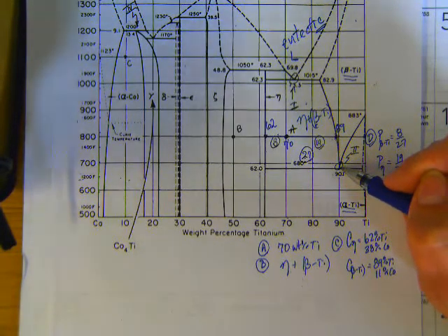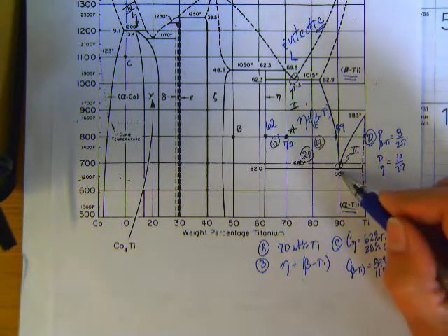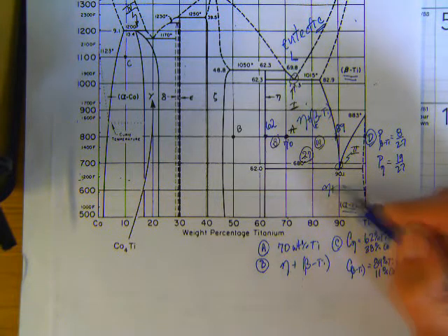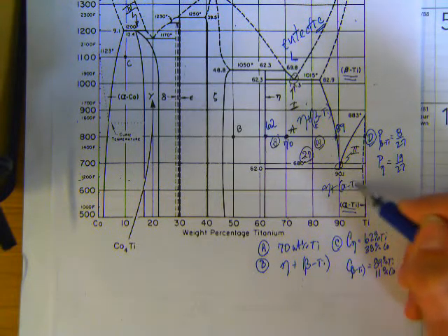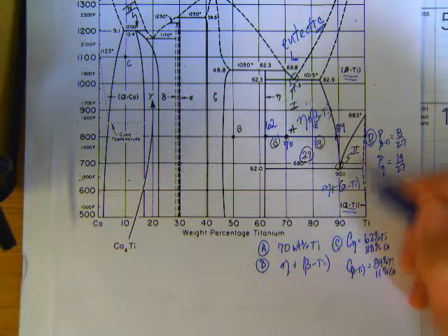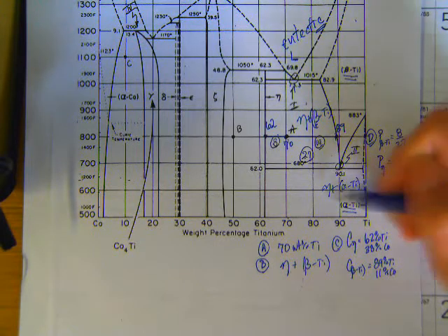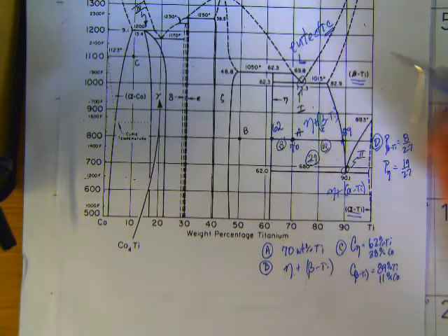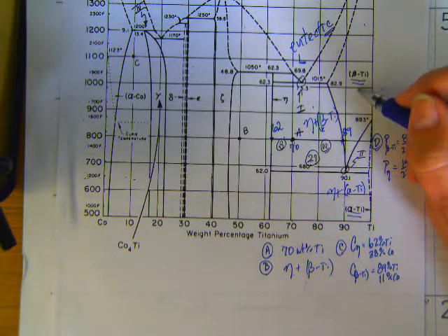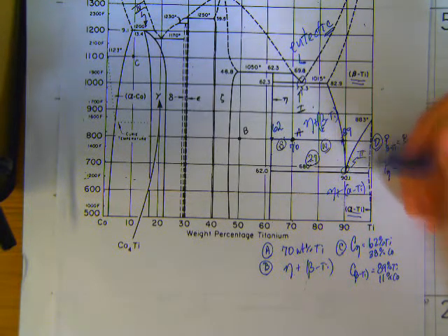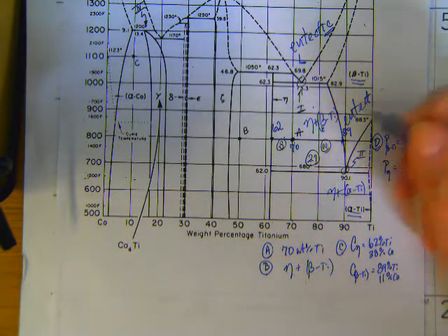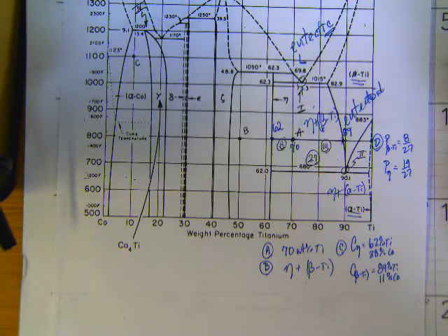Now we have an invariant down here at 90.1. Again, single phase, beta-titanium above. Down below, we now have eta plus alpha-titanium. So there's a crystal structure change. There's a big solubility difference. So there's quite a bit of diffusion needing to go on as beta-titanium transforms to alpha-titanium plus eta. So that's a single phase above turning to two below. And again, the single phase is above. So it looks like a U. So it's a eutect. But this is all solids. So it's a eutectoid reaction, not a eutectic.